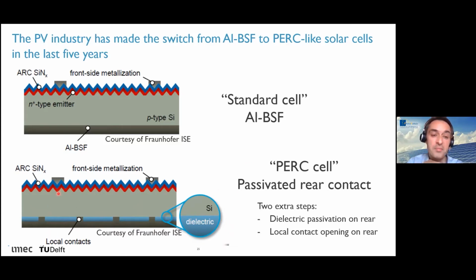Of course, it's a little bit more complicated cell structure. You actually need 2 extra steps compared to the standard cell. You need to deposit or grow in some way this dielectric. And then typically you have to use a laser to make openings in the dielectric to be able to contact it. But these 2 extra steps do not really add a lot to the cost. So actually this PERC cell now can also be produced at really low cost, but it gives much higher efficiency potential.